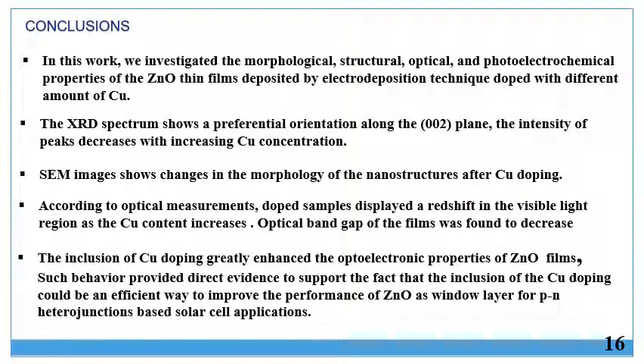Finally, in this work we investigated the morphological, structural, optical, and photoelectrochemical properties of zinc oxide thin films deposited by the electrodeposition technique, doped with different amounts of copper. The XRD spectrum shows a preferential orientation along the 002 plane. The intensity of peaks decreases with increasing copper concentration. SEM images show changes in the morphology of the nanostructures after copper doping.